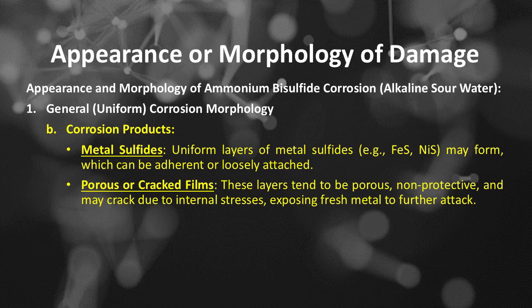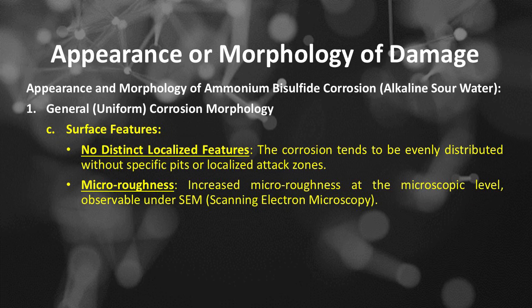Uniform layers of metal sulfides such as ferrous sulfide and nickel monosulfide may form, which can be adherent or loosely attached, porous or cracked films. These layers tend to be porous, non-protective, and may crack due to internal stresses, exposing fresh metal to further attack. Surface features of general or uniform corrosion include no distinct localized features. The corrosion tends to be evenly distributed without specific pits or localized attack zones.